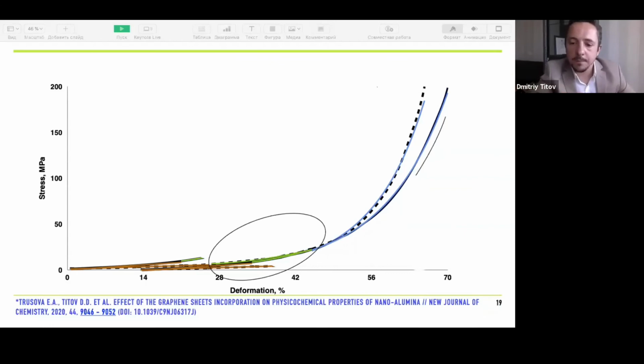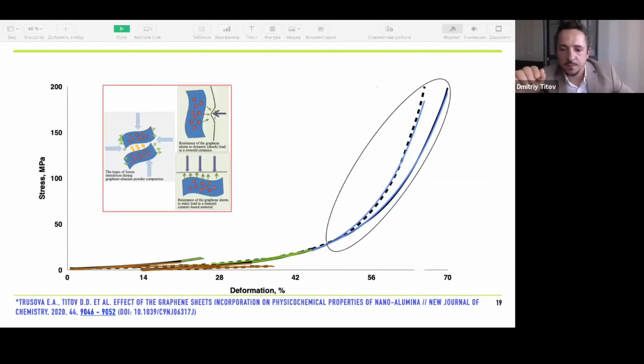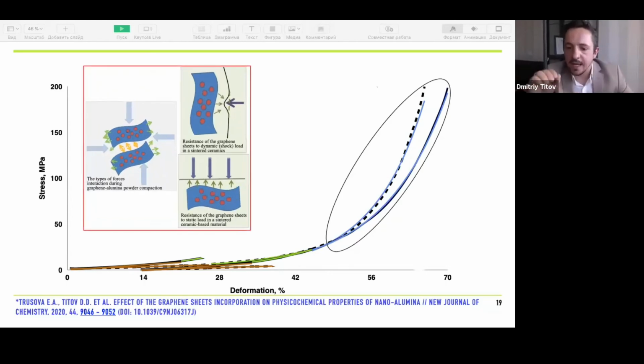If we compare the first section of both processes, we see that the angles of inclination are different. We assume that this is due to the elasticity of the graphene sheets. Graphene plays the role of nanosprings, so that the material has some elasticity and can be deformed more at this stage than the pure oxide, which, after occupying all voids, actively resists compaction. It turns out that it is the third stage that is determined in the process of forming hybrid structures with increased impact toughness.